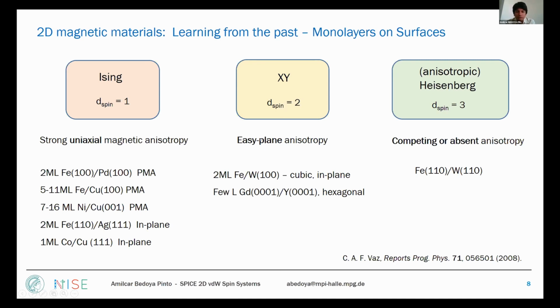For the XY, of course, you have an easy plane anisotropy. That means the spins prefer to lie in a plane compared to any other direction. There have also been some examples, at least much fewer than for the uniaxial case, simply because easy plane systems are much harder to get when you have a very crystalline and very strong crystal field. You can find all this in a very nice report. I'm giving the reference here. There's a huge list of materials that have been studied so far with in situ methods.